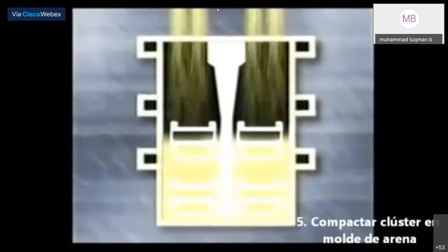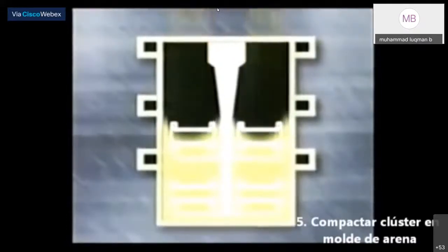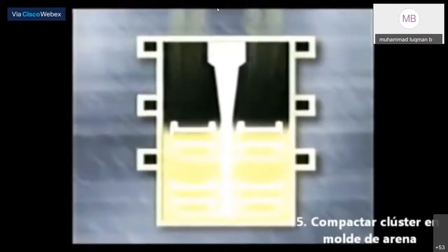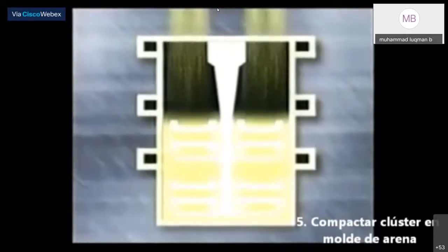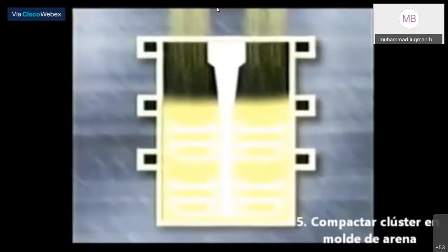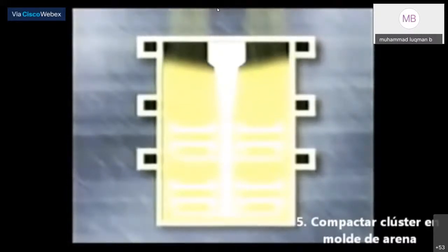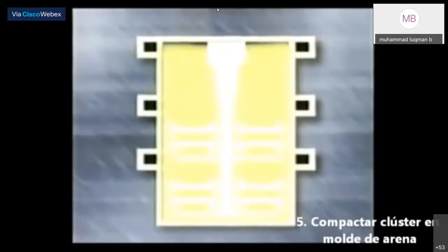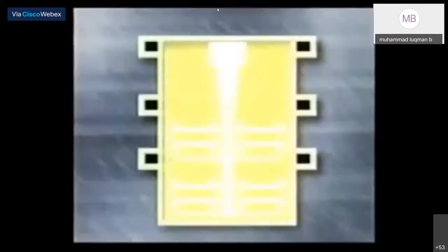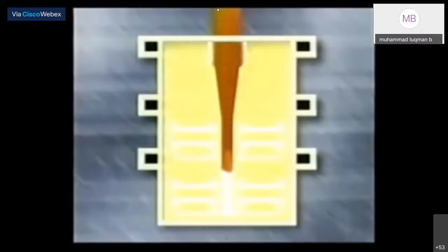Below the fluidized layer, the weight of sand above, together with vibration, causes the sand grains to move closer together, compacting. The vibration and the flowability of dry sand causes densities of the compacted sand around the coated foam to be 10 to 15% higher than in other sand processes. Proper control of vibration and sand fill can ensure low foam distortion and full rigid backing of the coating. Some systems use synthetic mullite in place of sand to further improve cycle times and dimensional tolerance. After fill and compaction, molten metal is poured into the cluster.